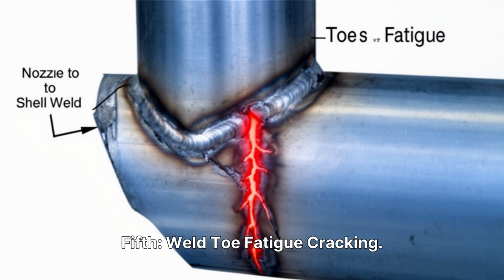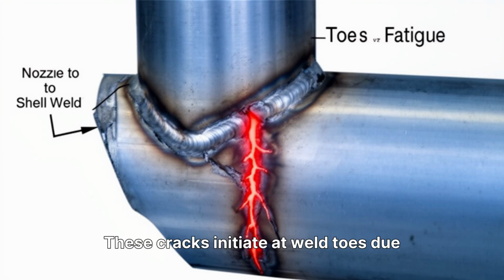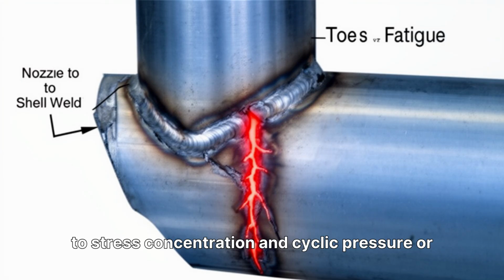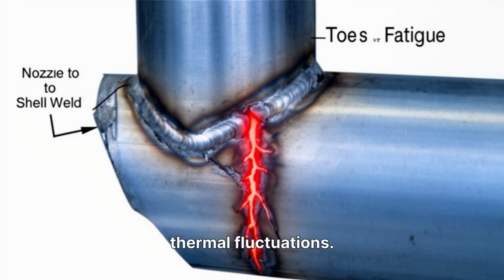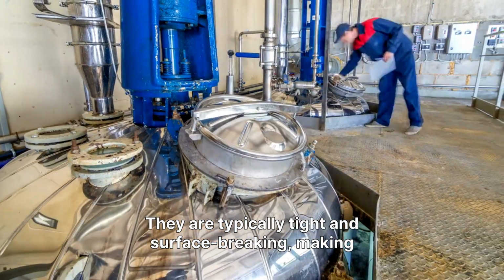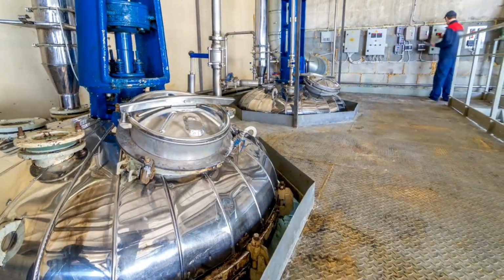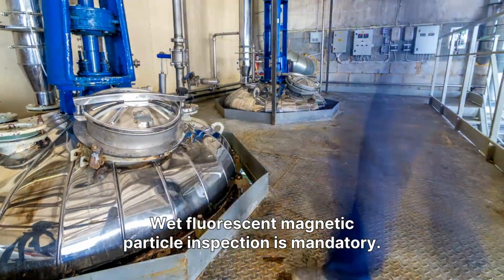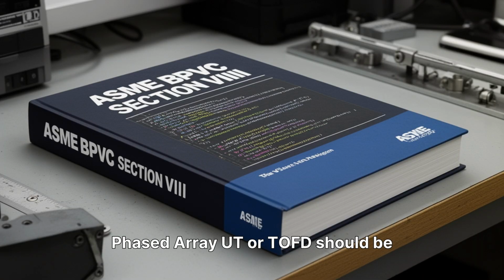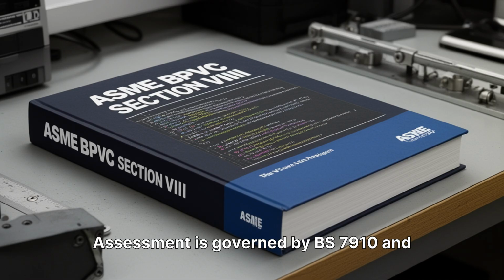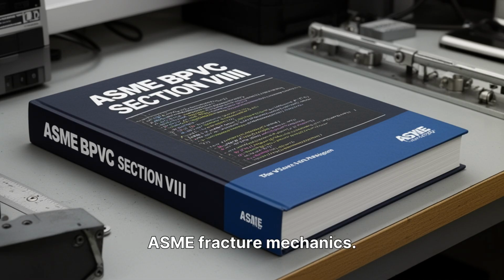Fifth, weld toe fatigue cracking. These cracks initiate at weld toes due to stress concentration and cyclic pressure or thermal fluctuations. They are typically tight and surface breaking, making them difficult to detect. Wet fluorescent magnetic particle inspection is mandatory. Phased array UT or TOFD should be used for subsurface characterization. Assessment is governed by BS 7910 and ASME fracture mechanics.